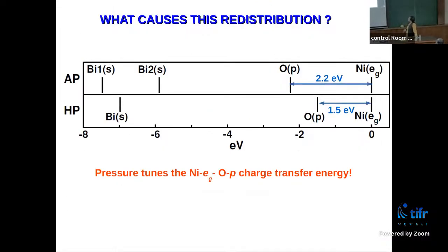And why does that happen? What causes this redistribution is nothing but that by putting pressure, you are tuning this nickel to oxygen p charge transfer energy. And there is a big change: at ambient pressure, this energy difference was 2.2 electron volt. In the high pressure, it becomes 1.5 electron volt. All you are doing is shifting the energy position of oxygen, nothing more. That's why initially oxygen was far from nickel and it was more happy to hold hand with bismuth. Now at the pressure, it becomes closer to nickel energetically and therefore holds hand with nickel. So what's the kind of pressure that you have? This pressure is 3.5 gigapascal.